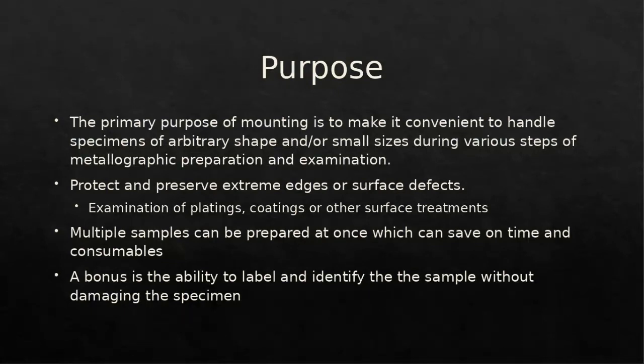Another bonus is that you have the ability to label and identify those samples without damaging your specimen. After you mount the sample, you can take a scribe, not a Sharpie marker, but a scribe, and etch the name into the side or the top of the sample that you're wishing to analyze. The reason I say do not use a Sharpie marker is that when you clean the samples between your polishing steps, which we'll discuss later in the grinding and polishing process, the Sharpie marker will tend to come off. And if you have 10, 15 samples, the last thing you want to do is mix those samples up.